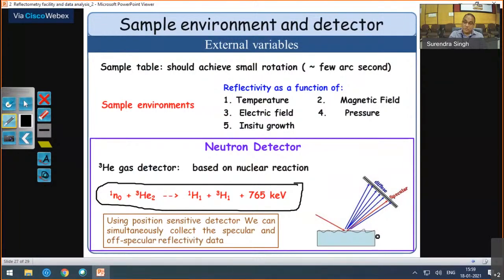If you have sample rough interfaces, thin film sample, and neutron beams falling on that, then you will have all kinds of reflection from there, specular as well as diffuse. And if you use this position sensitive detector, you will be able to use both specular and diffuse reflectivity simultaneously. Okay, so this completes the instrument part of neutron reflection.